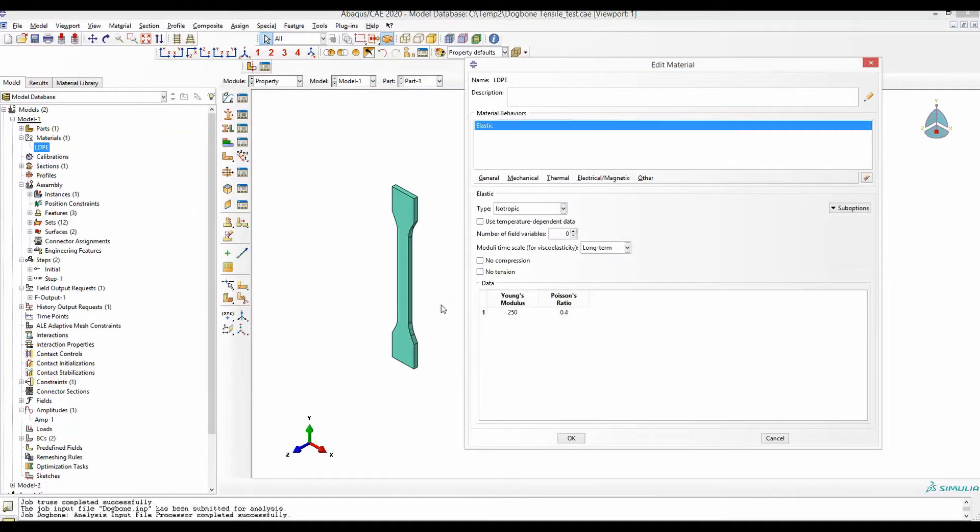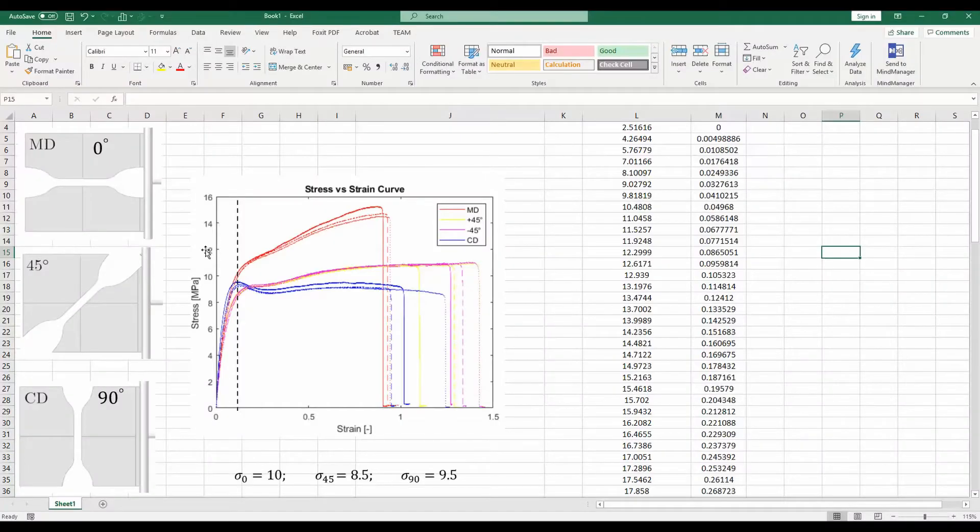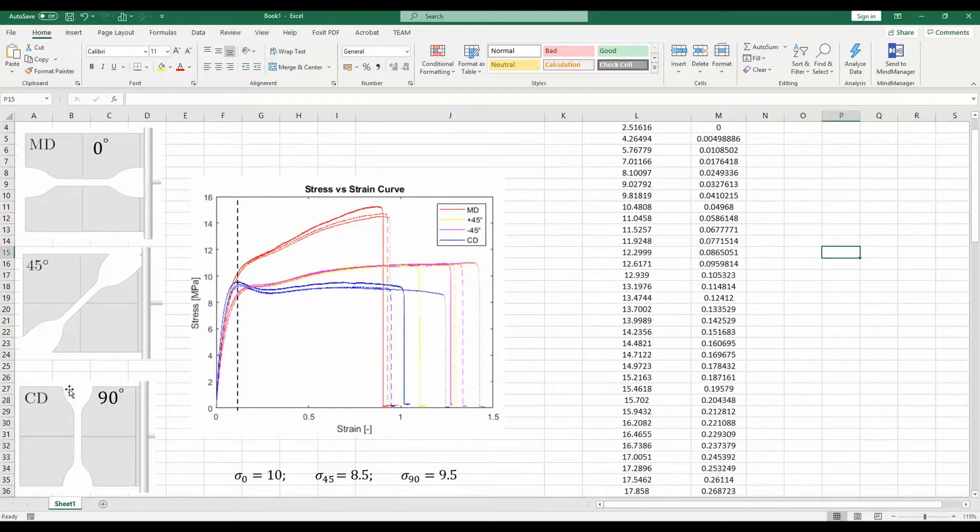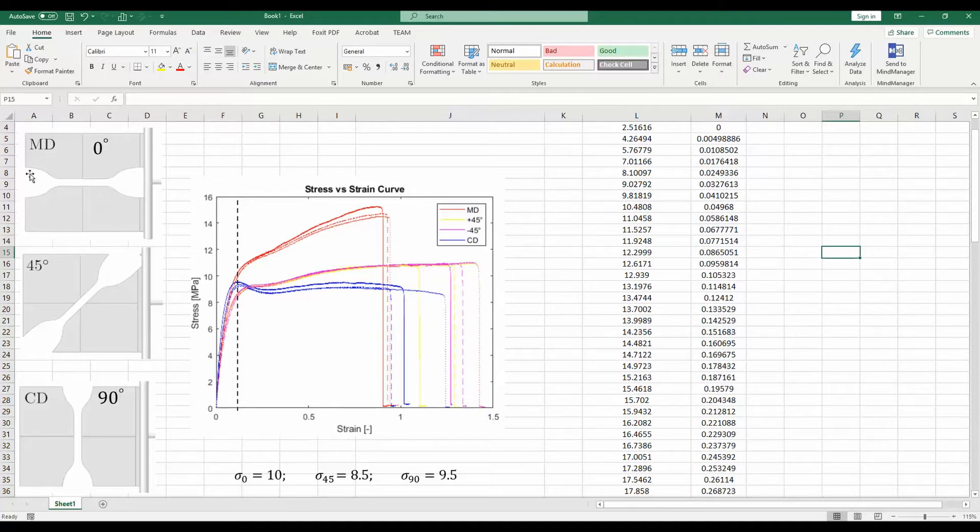In this video, I will show you how to simulate this model using the Hill48 anisotropic material model. To define the Hill48 criterion, you need to take your material and cut three specimens in 0 degree, 45 degree, and 90 degree orientations. The specimens need not be dog bone; they can be simply rectangular specimens.